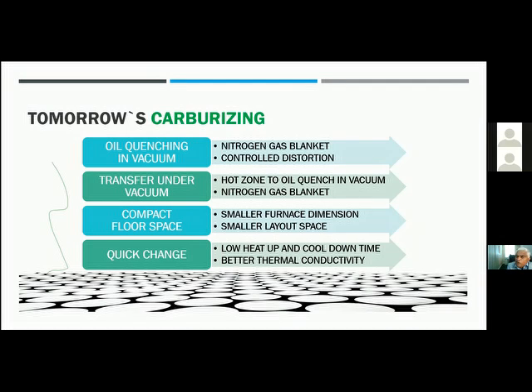Even the transfer of the product or the component or the grid from the furnace hot zone to the quenching is under vacuum. And so there is absolutely, again, no contamination of oxygen when you transfer, again using nitrogen. It's all under partial pressure.